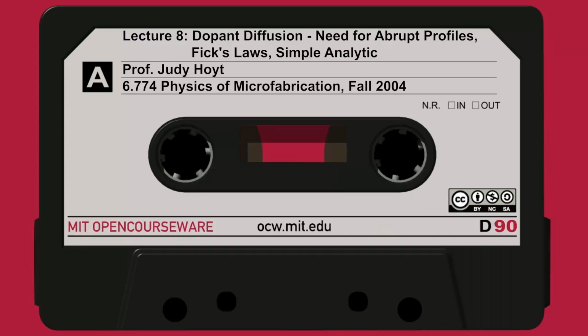And then we're going to let it diffuse out, and as it turns out, we'll see if the diffusivity is a constant, it diffuses into the shape of a Gaussian profile. So basically the boundary conditions are that we have essentially a delta function at time t equals 0, and that the dose, the integral of this delta function, is a constant.